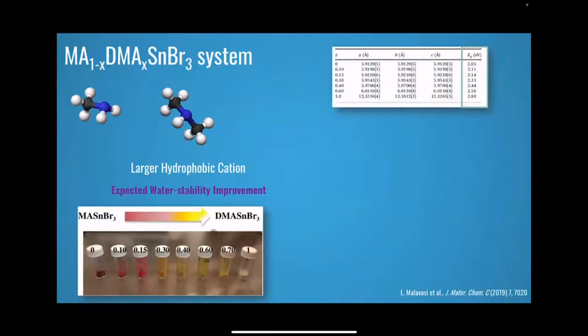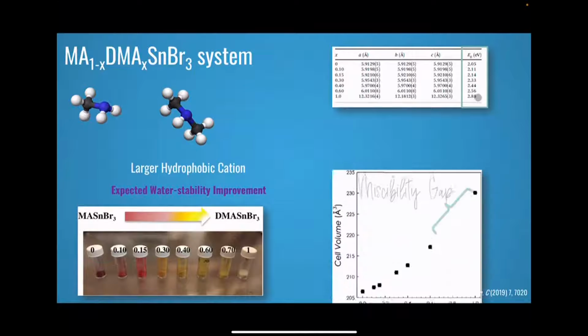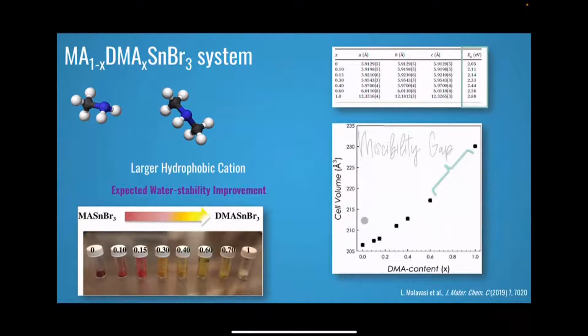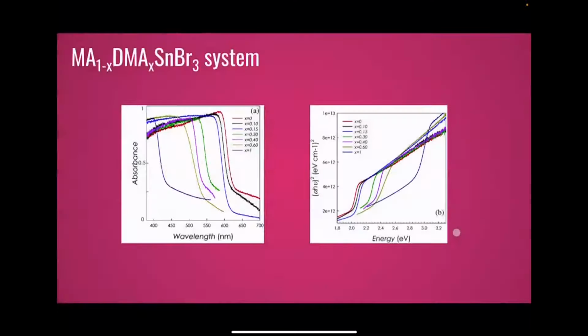Anyway, we prepared, for example, this solid solution. You see that when you move from methylammonium tin tribromide to dimethylammonium tin tribromide, the color of the powder changes. The band gap moves from about 2 eV to close to 3 eV. Okay, there is a miscibility gap. You cannot prepare the full solid solution, but these are details. Here you see some absorption spectra in the Tauc plot of the series by changing the relative amount of dimethylammonium, starting from the red, which is pure methylammonium tin tribromide, to dimethylammonium. Anyway, these are the basics. You can have a very good band gap tuning just by replacing the organic cation.